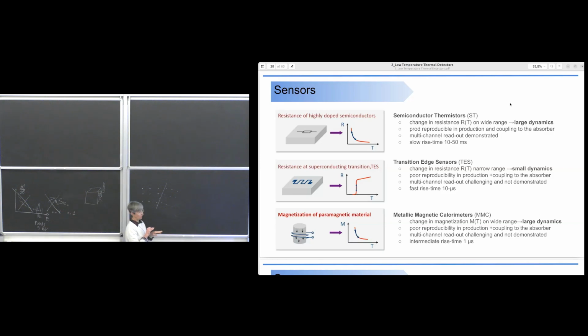It's not easy to tune the transition for all the sensors in your array of crystals at the same temperature, but the temperature is the temperature of the cryostat. So otherwise, you have to add a heater on each of the crystals, and control the heater in order to tune the temperature. Also, the coupling to the absorber is not easy. It could depend on the kind of absorber, because the interface between your alloy and the surface of the absorber is important, and sometimes the matching is not optimal, and so you have to add something in between.